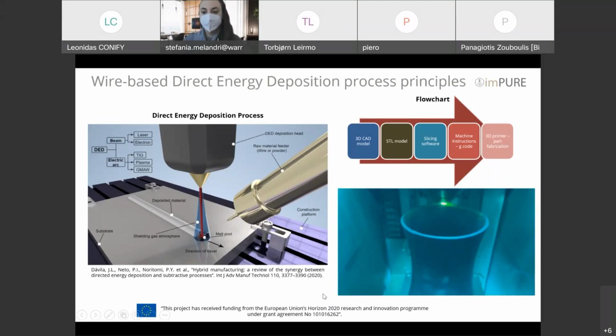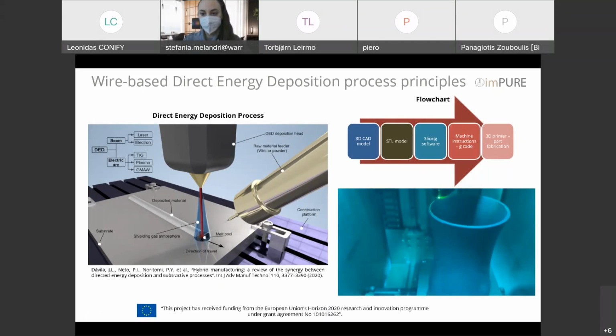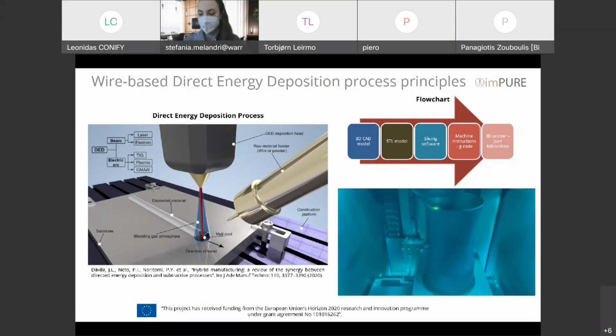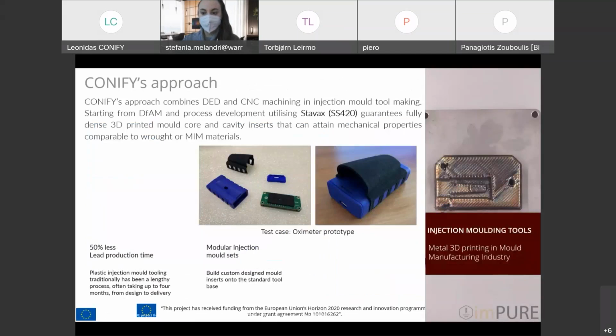Yes. So this is an example of the wire DED process. In this case, this is a nozzle. So this is how the process works. The deposited material is melted in the melt pool by the laser, and layer by layer, every time we move our layer one step lower, we deposit more and more material on top until the final part is completed. So next slide, please.